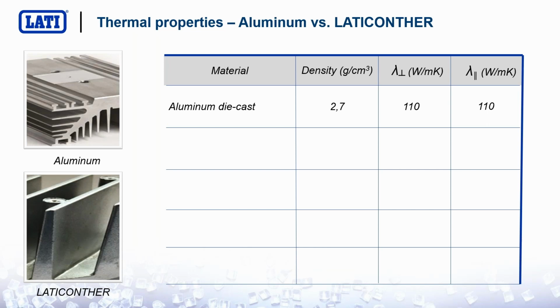The density of die cast aluminum is 2.7, and its conductivity, along plane or through plane, it makes no difference, is 110 more or less, which is lower than elemental aluminum. Elemental aluminum is as high as 200 watt/meter Kelvin, something like that. But actually, we have to focus our attention on this number, more than 100 watt/meter Kelvin.